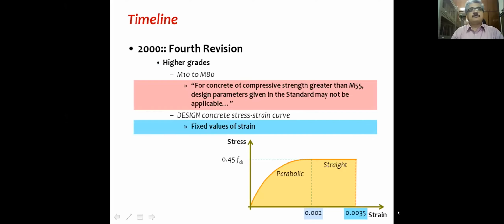What the 4th revision did was acknowledge that by then a lot of higher grade materials, particularly concrete, had come into the market, and the code allowed use of up to about M80 concrete. But in a small note, it says that for concrete compressive strength greater than M55, design parameters given in the standard may not be applicable. This led many engineers to fall back on other international standards because our own IS 456 did not provide a solution.